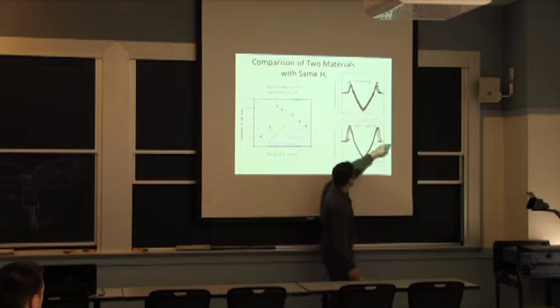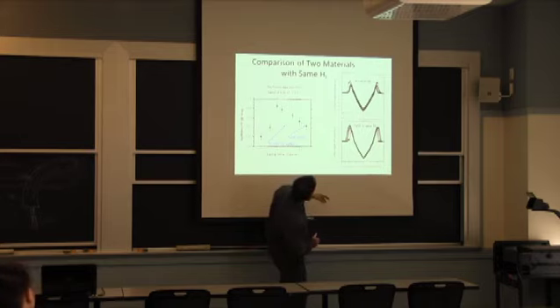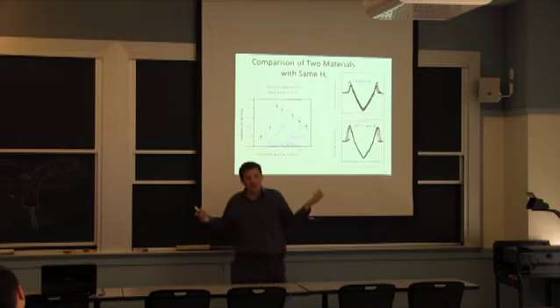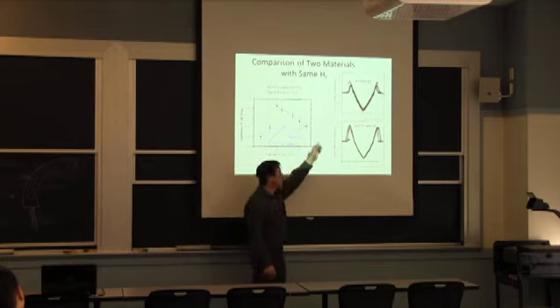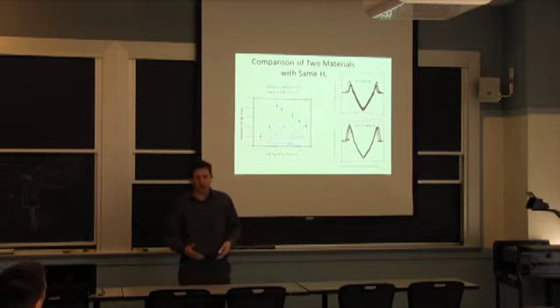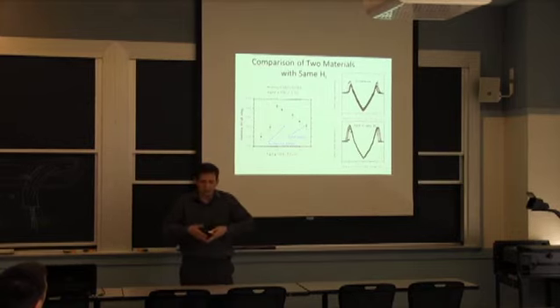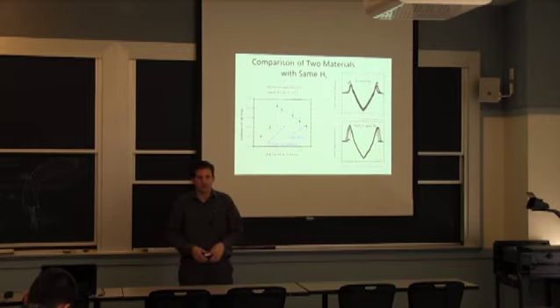So we're looking at a cross section that's normalized, and you can see maybe a factor of about 2 in how much material is getting pushed out of the scratch to the side when you have that overage condition. And that's an exemplification that you have less hardening. If you have a material with a lot of hardening in the normal indentation test or a scratch test, it will essentially consolidate and it will not extrude out as much material as a material with a low hardening.